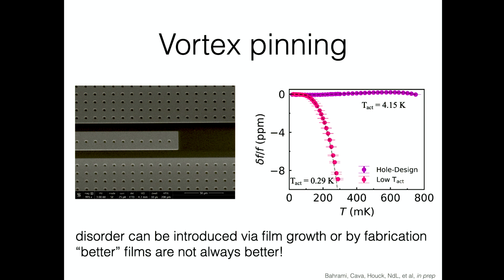Okay. All right, so this is a very detailed story, but I think the detailed takeaway for anyone who wants to work on tantalum is that this disorder can be introduced either via film growth or by fabrication. The differences in the films are actually pretty subtle. But maybe the broader message for material scientists is that better is not always better. This was a case where we tried to make the most perfect films we could, and then we ended up with worse device behavior at the end.